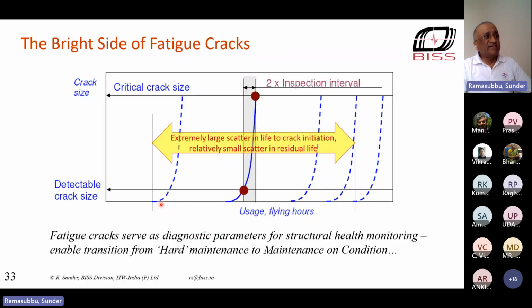The scatter in fatigue crack growth life, this is the residual crack growth life, is much less than the scatter in fatigue life. And because of that, as long as you assign an inspection period, you're safe. And you can continue to use the structure for as long as it will serve without worrying about the possibility of catastrophic failure.